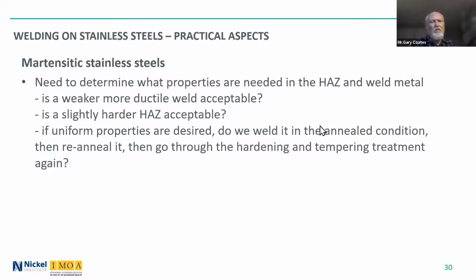So, one of the complications, shall I say, when welding martensitic stainless steels is that you need to determine what properties you want in the heat affected zone and the weld metal. Can you live with a weld that is weaker but more ductile? Can you live with a slightly harder heat affected zone